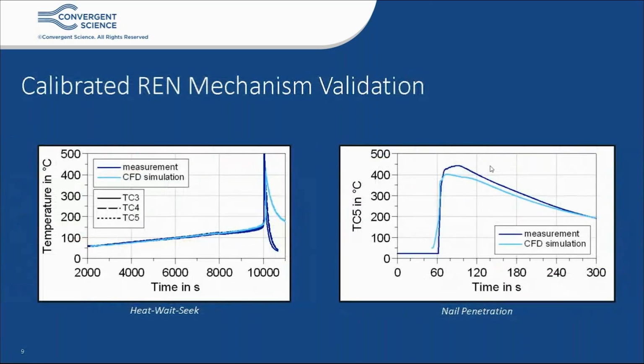Once we got a calibrated REN mechanism, we forwarded that mechanism to IAV engineers. They constructed Converge simulations for a heat-wait-seek experiment and a nail penetration experiment, and that calibrated mechanism accurately reproduced the experimental behavior for those different tests. So we can be confident that our calibrated mechanism will work well for different types of simulation scenarios.